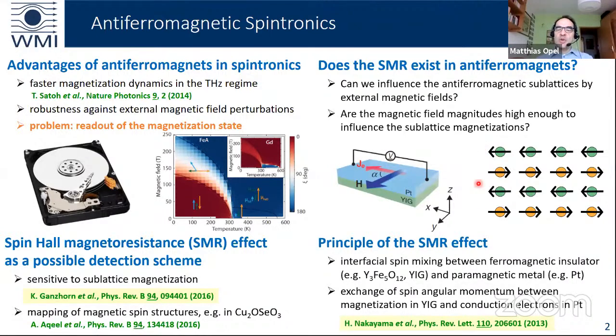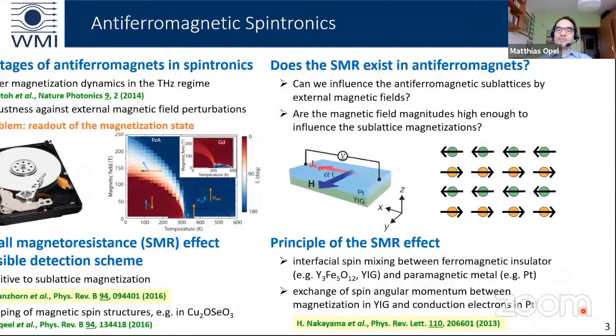First of all, I want to show you the principle of the SMR effect, and it is based on an interfacial spin mixing between a ferromagnetic insulator, that was in the first experiments yttrium iron garnet, or short YIG, and a paramagnetic metal with a large spin-orbit coupling. In the first experiments, this was a metallic electrode of platinum. And then, in contact of these two materials, it comes to an exchange of spin angular momentum between the magnetization in YIG and the conduction electrons in platinum.